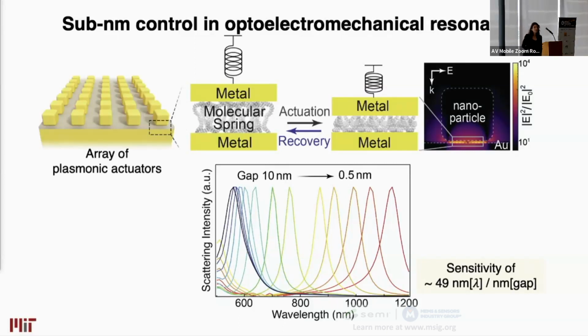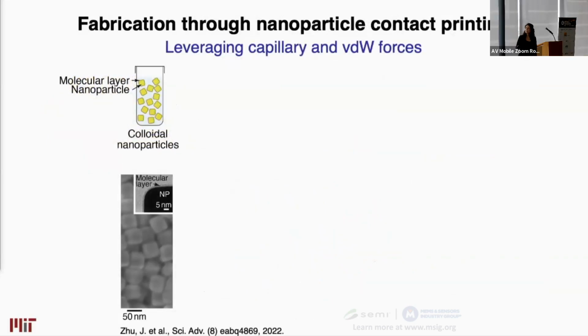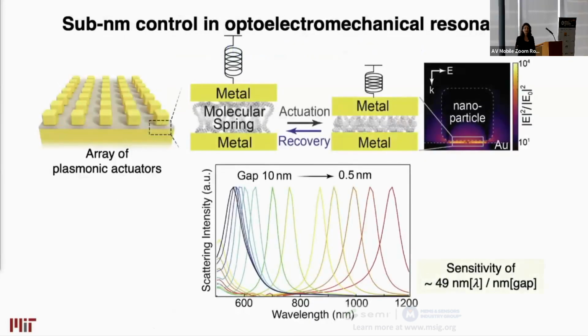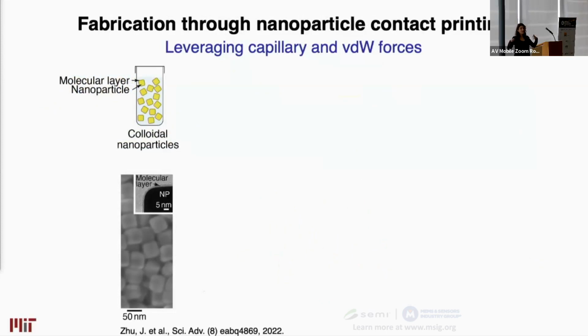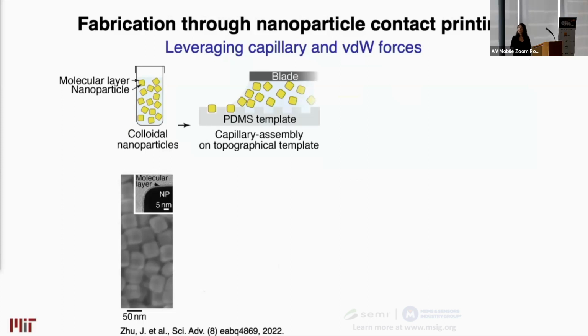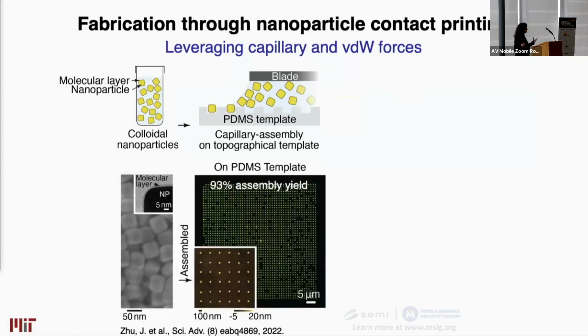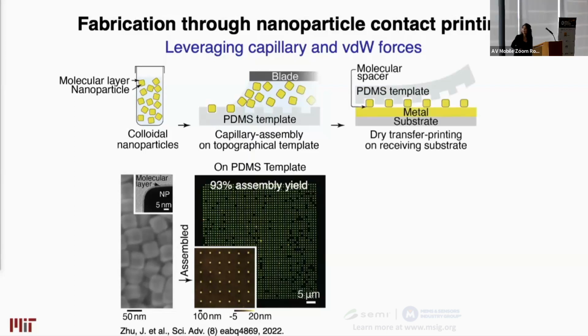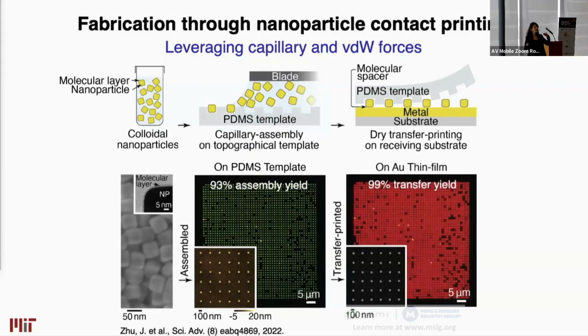A step towards this is to be able to fabricate these structures at scale. And we do that, again, by implementing a technique based on integration of top-down and bottom-up techniques. We start with scalable synthesis of colloidal nanoparticles, here nanocubes, as our building blocks, and we come up with ways of spatially assembling them in the order we desire. You can see here on the dark field image the assembled nanocubes. Every green dot you see is an individual nanocube. The nanocubes can then be transferred onto arbitrary surfaces, in this particular case a metallic mirror, so that you can create your plasmonic resonators.